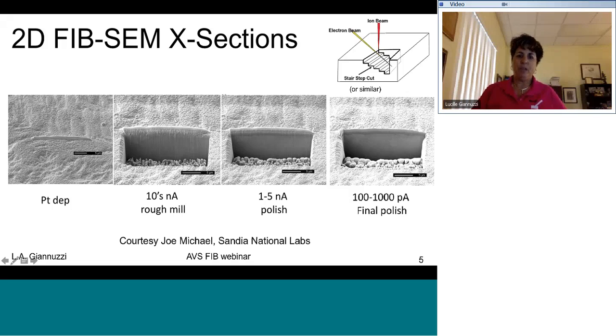So the idea is to make your first cut somewhat away from the original deposition, and just make the cut. In this case, this is called a stair-step cut, or you can FIB mill line by line using so-called clean cross-section or line-by-line milling. And the idea is you don't have to cut away the entire section here because you're not going to be able to see into that anyway. So this just saves time by milling the so-called cut that gets deeper and deeper towards the region of interest. So you use a large beam current. This can be tens of nanoamps for the rough mill. And as you approach the region of interest, you use finer and finer beam currents until you do a final polish at somewhat less than a nanoamp or less, depending upon what you want to image. Okay.